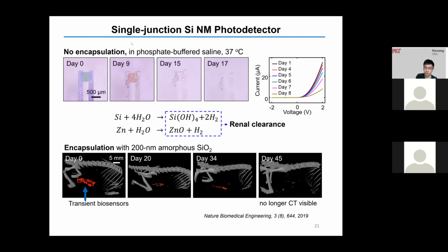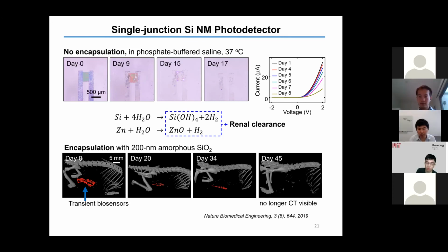So that set up the dissolving time scale for such silicon nanomembranes, which means if we want to treat silicon as a bioresorbable material, we have to design such devices in the context of its dissolving behavior. If it's 200 nanometers, it may dissolve within a couple of months, maybe a few weeks. That can be used as a transient material, but a 500 micrometer silicon wafer put in the body may take 200 years to dissolve. That's more than a lifetime, probably. So it cannot be treated as a transient material.